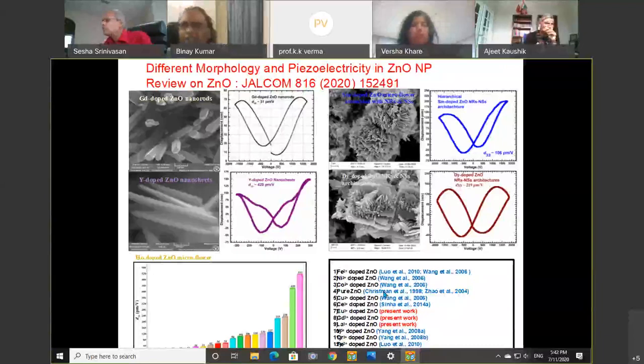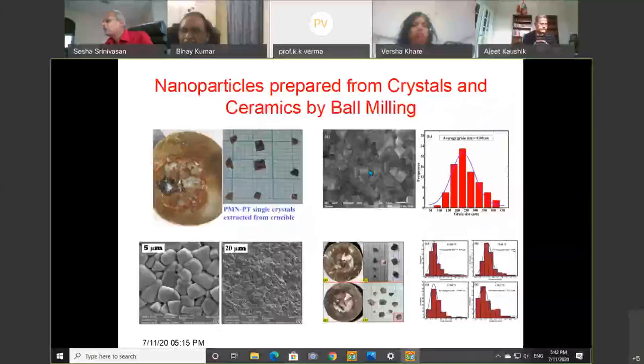So I am not showing our ball milling. It takes almost 4 to 5 days or even more of continuous grinding. And we ultimately get nanoparticles of sizes close to few nanometers in one dimension, and the average dimensions up to a few hundred nanometers. This is a particle size analyzer, which gives a very rough idea. It takes the average of all the particles, but there are many particles which are smaller in size.